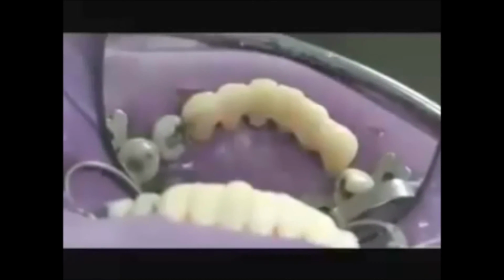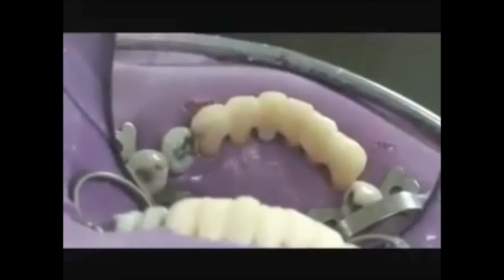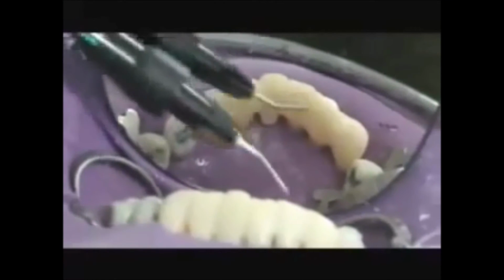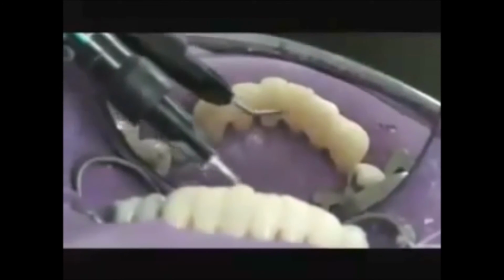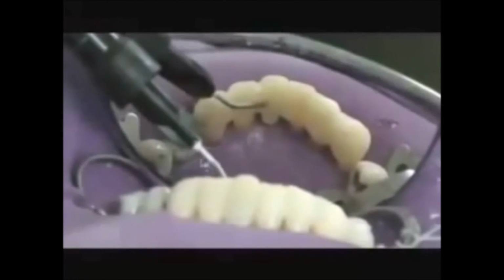I'm finishing and polishing the lingual surfaces as well, making sure that none of the fiber reinforcement material is sticking out, is perforated through the composite. After my preliminary finish and polish, I inspect to make sure the fiber's embedded. If I see areas of exposed fiber, I can cover them with a flowable composite and then light cure that flowable composite resin and then polish those surfaces back up. With the flowable in place, where I've placed it, I'll light cure those areas for 15 to 20 seconds.